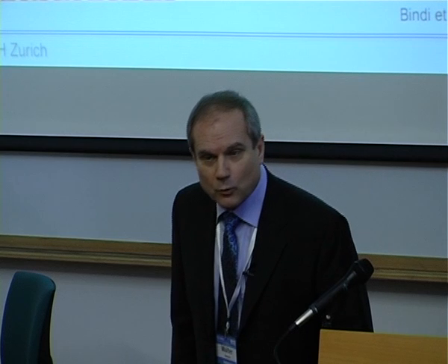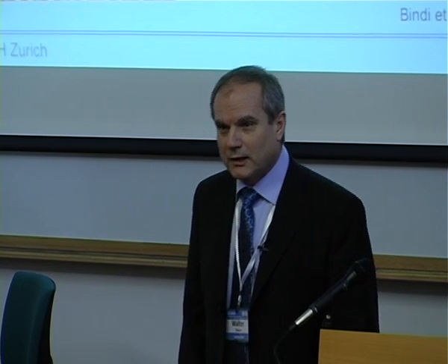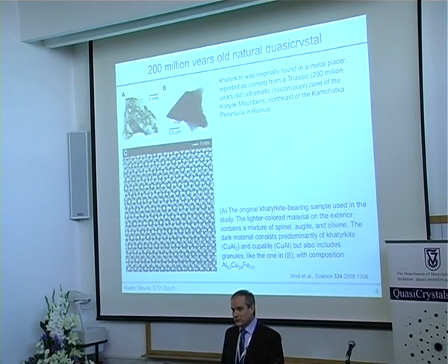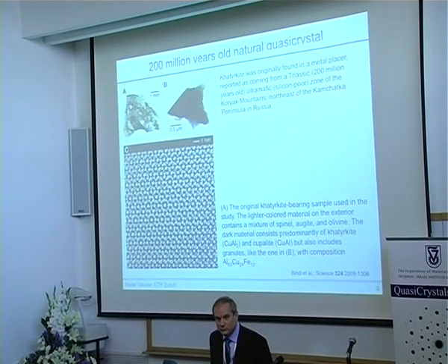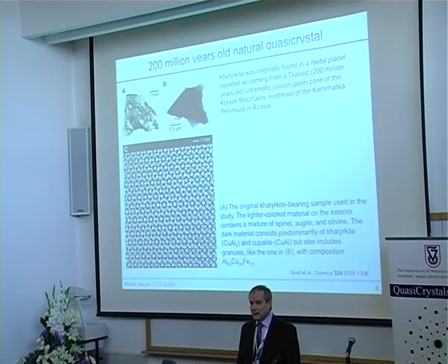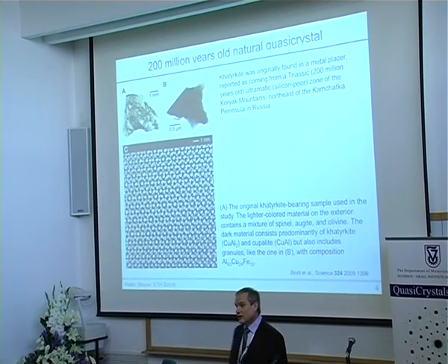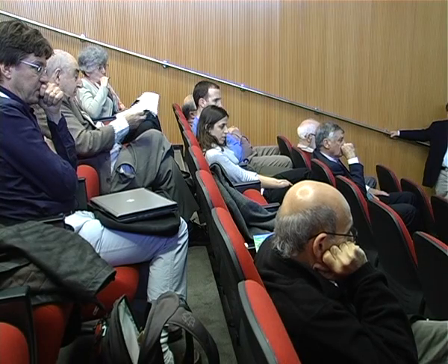And you see here a TEM image of such a quasicrystalline inclusion, and this image looks like it should look for a quasicrystal. And this means, since this mineral was formed 200 million years ago, that quasicrystals can indeed be stable for such a long time. This is one of the questions, how quasicrystals are stabilized, more by entropy or more by energy or both together. And since at low temperatures, phase transformations to periodic structures are of course very, very sluggish, it takes a long time. And this at least tells us that quasicrystals seem to be pretty stable.